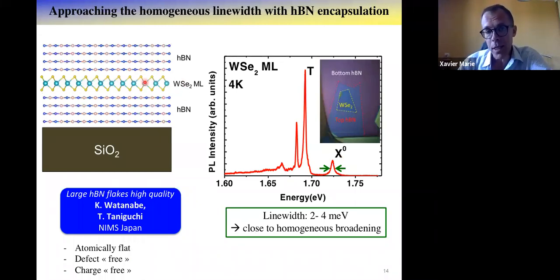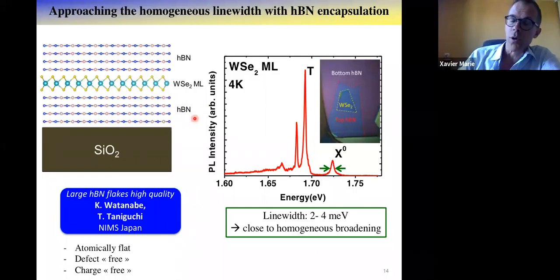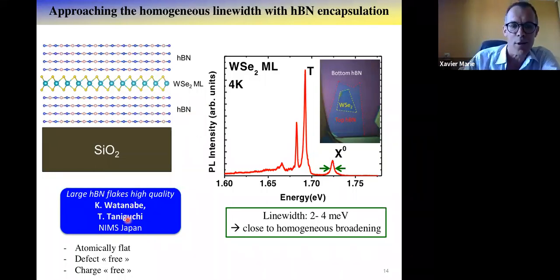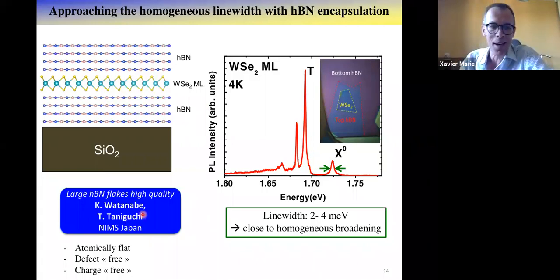By encapsulating the monolayer inside a well-controlled dielectric environment, where we use here hexagonal boron nitride, it's single crystal, high quality, and like almost everybody in the world, we use one from NIMS in Tsukuba. It's a single crystal, atomically flat, probably with a very low density of defects inside. And on top of that, we protect the surface with this top hBN. So you fabricate this basic van der Waals heterostructure, and you improve drastically